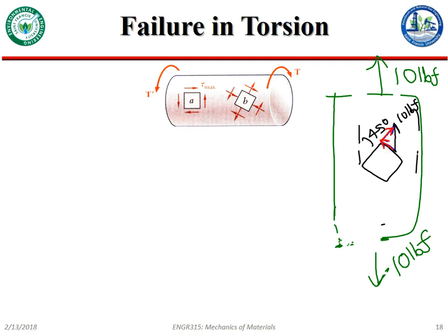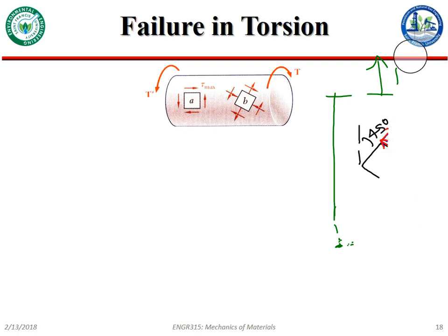And we said, okay, ductile materials are more sensitive to shear stress, so they'll fail on that maximum shear plane, which is at 45 degrees to the long axis of the material, at least when you have tension and compression loading, and that's why you get these angled breaks, some which are really darn close to 45 degrees. However, in torsion, it's a little bit different.